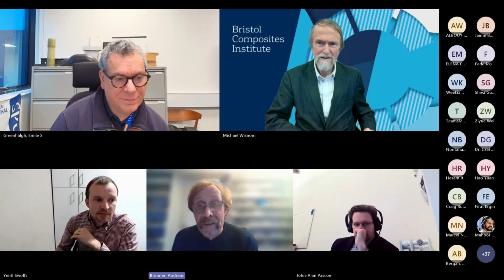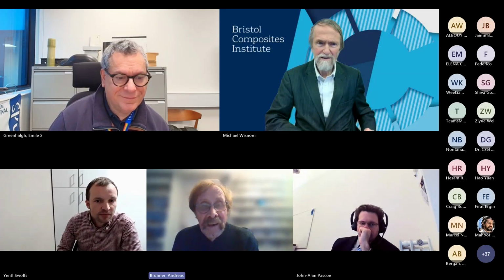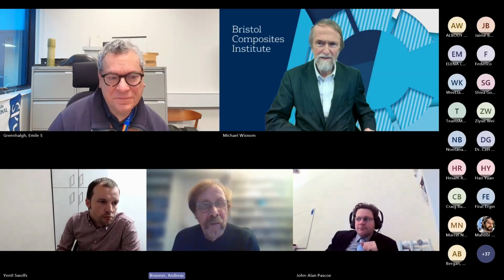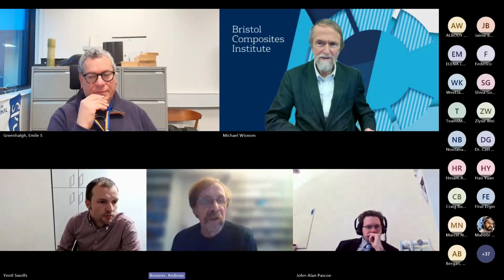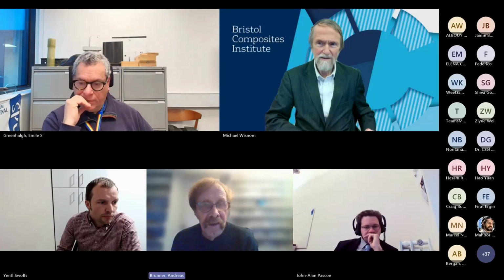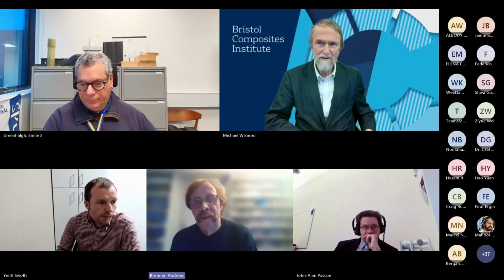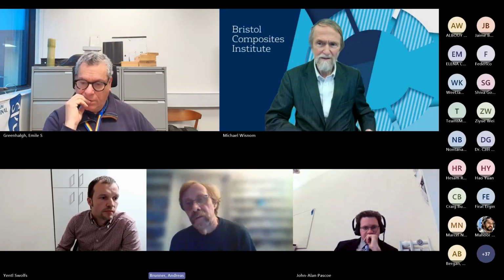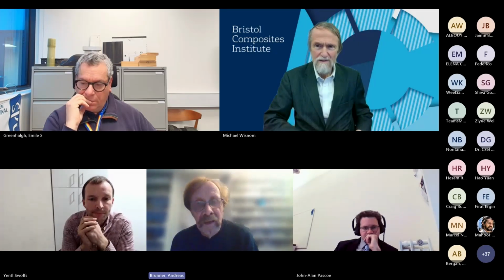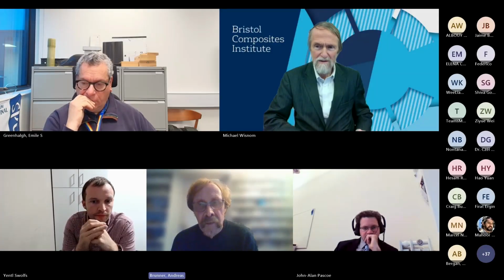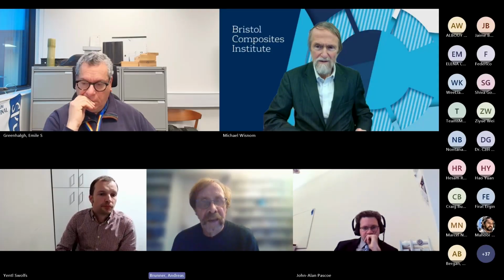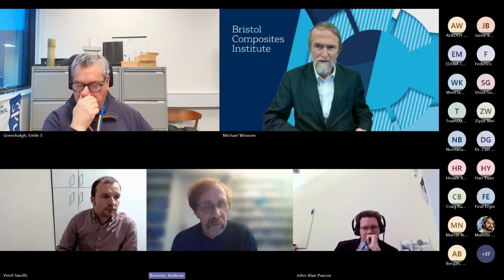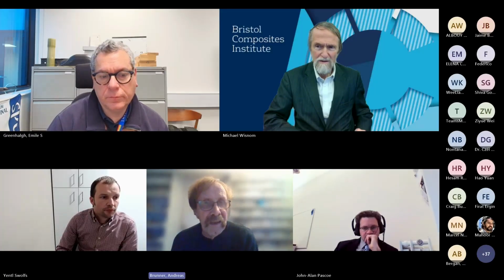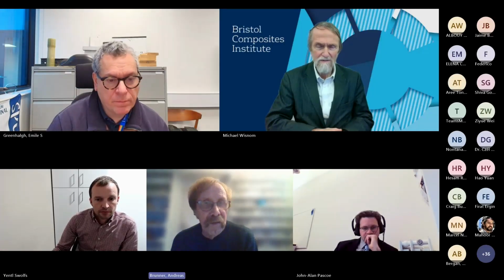Yes. The main reason I brought it up is just to stimulate discussion. As I hopefully managed to point out, it's a question of how much you want to be on the safe side or how much risk you can take in designs. I was trying to balance this regarding the type of tests. Mode 1 tests are simple, straightforward, and don't need much material, whereas a mixed mode test is already more complex, even if you use the MMB. Independent of which test we use, we may have to keep an eye on the scatter. The intrinsic scatter, which comes from measurement resolution, tends to be fairly low, a few percent. But the round robins indicate 10 to 20, 25% of scatter.